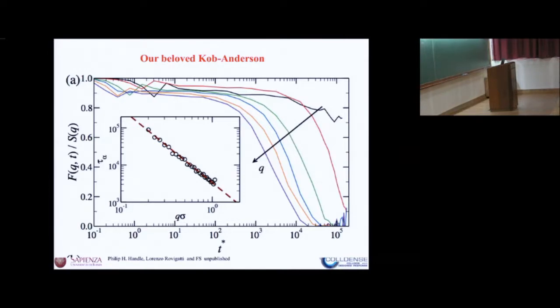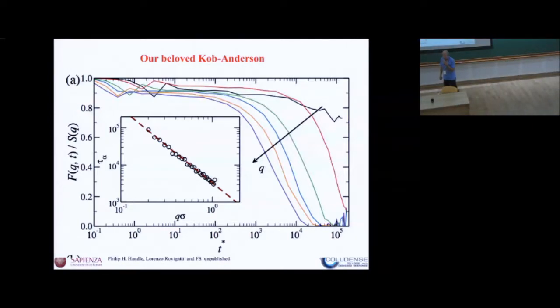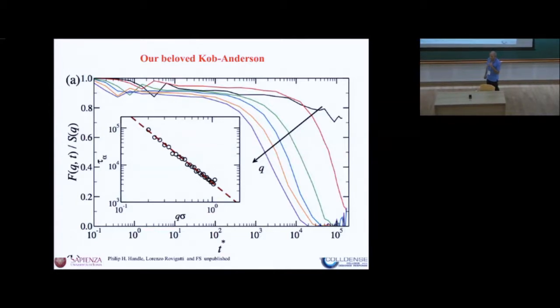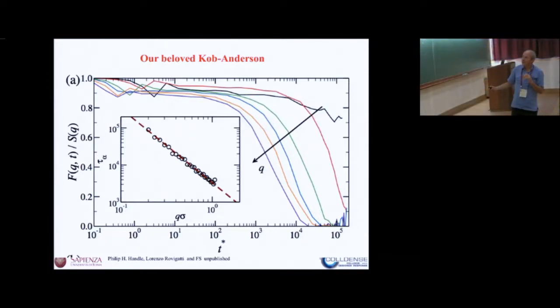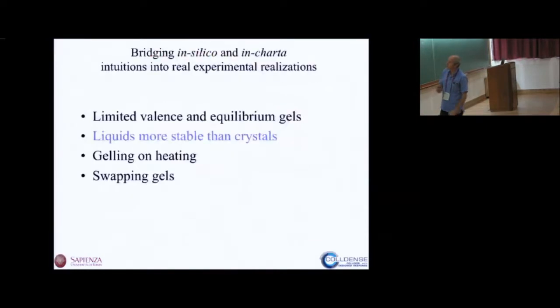Now, this is also interesting for simulations because if you really want to study a big system with a binary mixture like this one, you better be careful because it would take a huge amount of time to really equilibrate. It will be almost impossible to equilibrate a 1 million particle binary mixture Lennard-Jones if you want to be careful. Because there is a characteristic time that goes with Q to the minus 2. You really have to wait until all the small q have equilibrated. So this is the slowest time in the system. It's not the alpha relaxation time of the peak. This is the slowest relaxation time that you have in the system. We have also to be careful to look at this type of things.